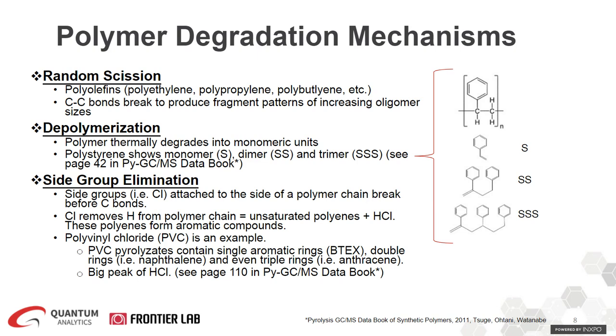In a side group elimination, PVC, polyvinyl chloride, can be a good example. In this case, the side group, that is Cl, which is attached to the side of the polymer chain, breaks before the C-C bond breaks. So the Cl removes the hydrogen from the polymer chain. Some unsaturated polyenes plus the HCl will form. Then these polyenes form aromatic compounds such as benzene and naphthalene.